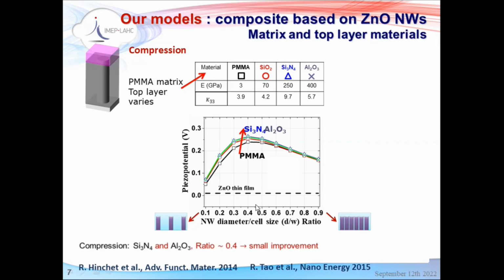So you can see immediately that somewhere there is an optimum for the density of the nanowires that we could fabricate. And then another thing is that if you include more rigid materials at the top here, you can eventually improve the performance as well. Something interesting is that if we simulate a thin film, meaning that it's only zinc oxide here, you can see that the composite outperforms this zinc oxide. So only by the structuration and the fact that it's a composite, you can already change the performance and improve it.